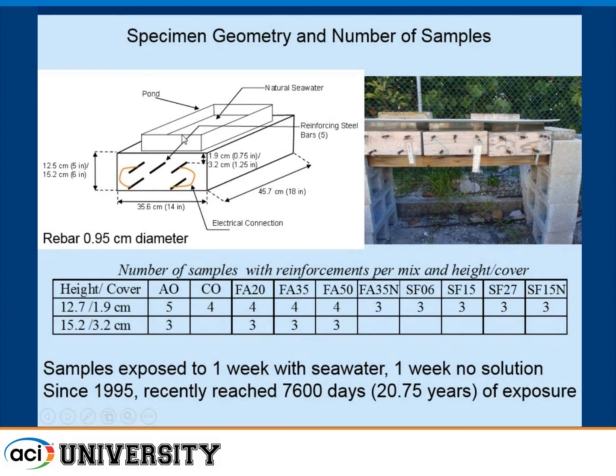And this actually took place, the samples were prepared in 1994 during the fall. Incidentally, that's the summer that I came to the US to start my PhD studies. And then they were transferred to Florida Atlantic University in early 1995. And since then, they have been exposed to fresh seawater, 1 week wet and 1 week dry. Additionally, as you can see from the picture, with some of the greenery there, they are exposed outdoors, so they are also exposed to the temperature and humidity changes that might be taking place during that time. So by now, we have 7,600 days, so close to 21 years of exposure.